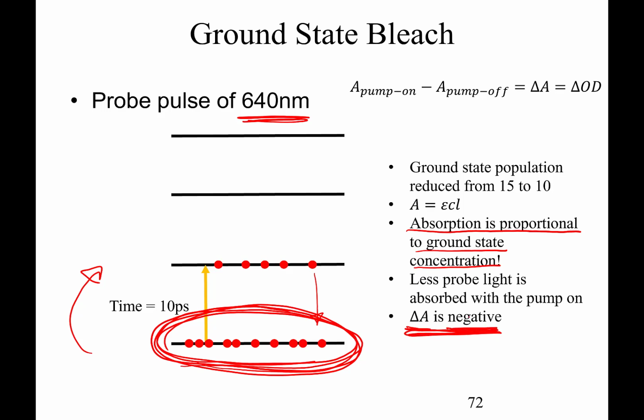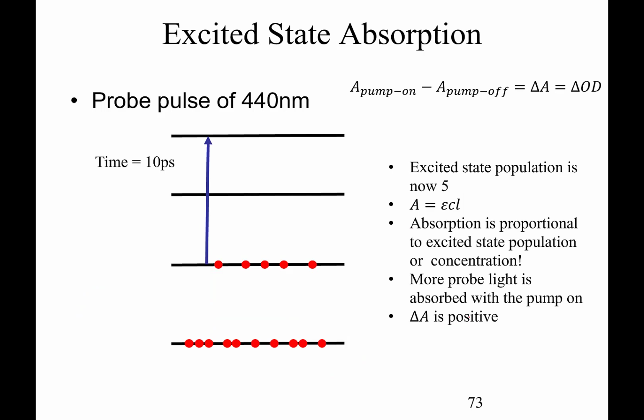On the other hand, if we come in with a probe pulse of 440 nanometers, what we now can address is a transition from, let's say, this second state here up to this fourth state. And maybe this transition here is an energy that's associated with a wavelength of 440 nanometers. So the absorbance at 440 nanometers will actually go up because now we have molecules in this state down here that can actually be pumped up higher into the fourth state.